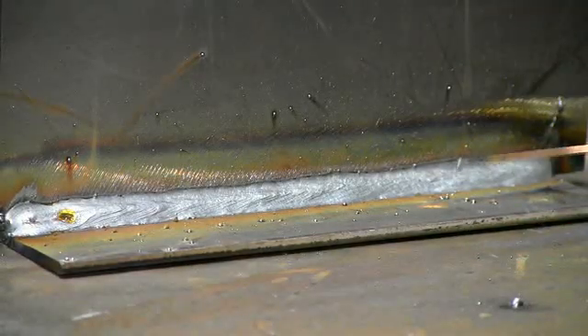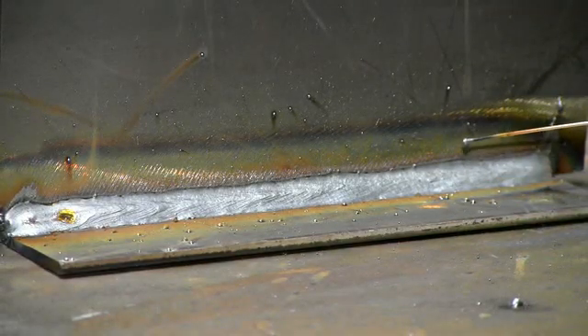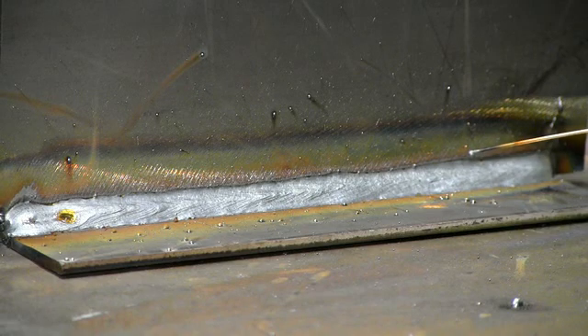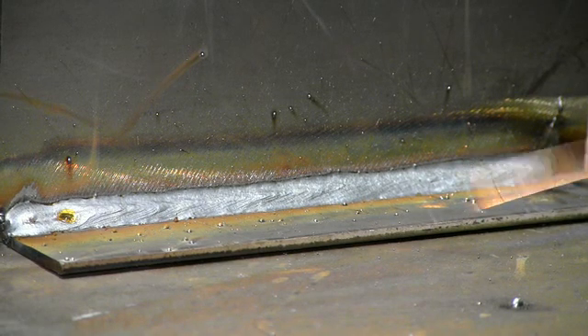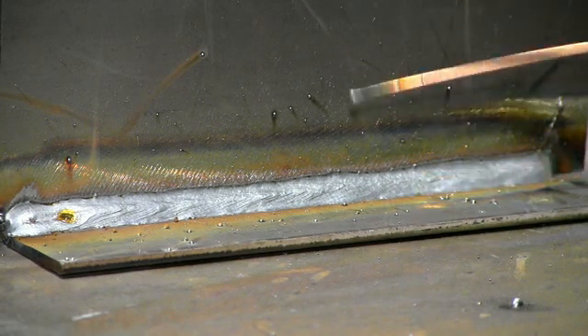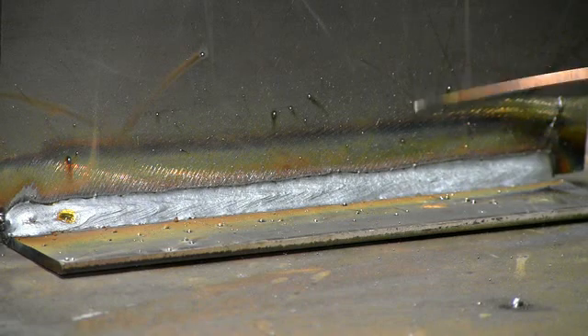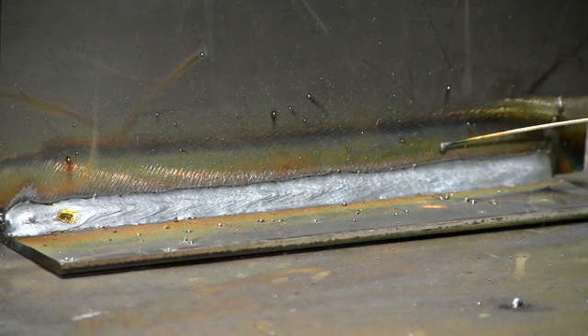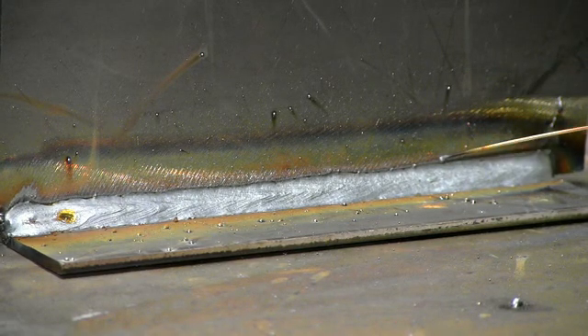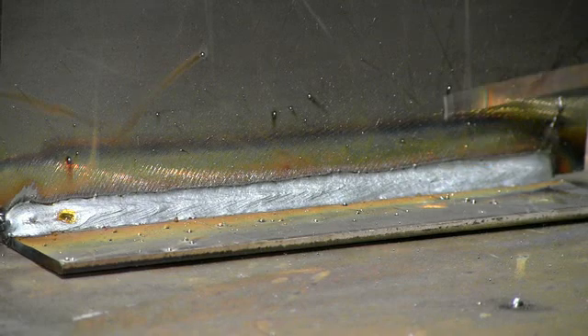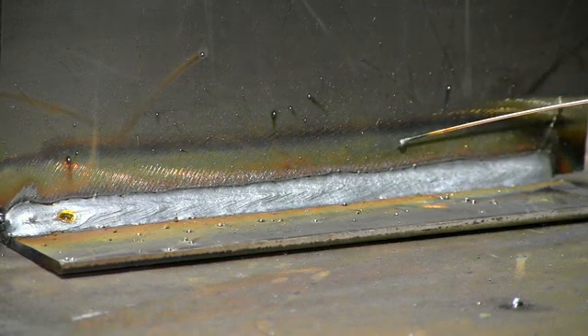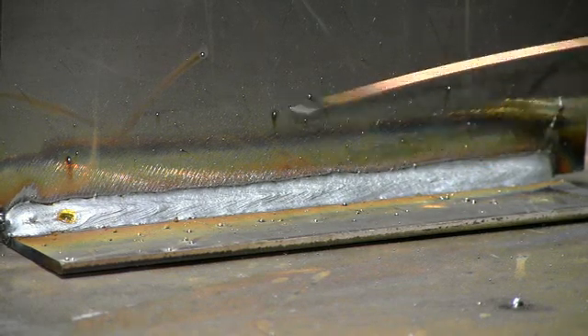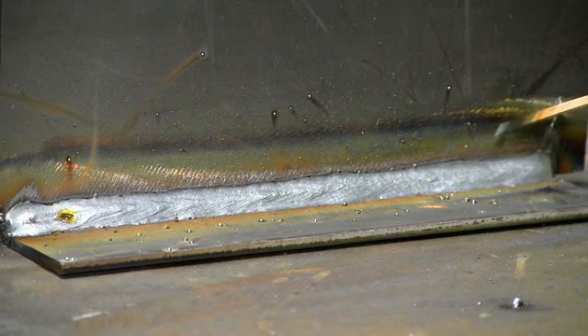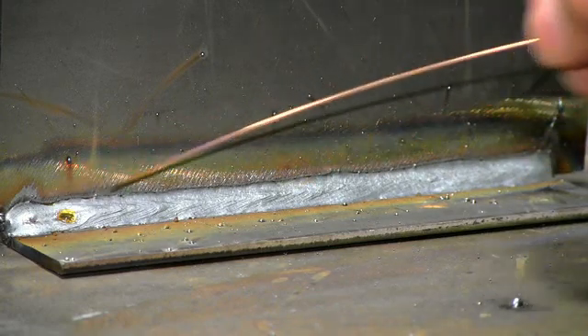So now you can see the results of welding at 700 inches per minute at 27.5 volts. Our optimum settings again were 27.5 volts and 600 inches per minute. In this test, I raised up the wire feed speed to show the impact. And so what was happening while I was welding was the electrode was kind of cramming into the puddle, and this was causing the arc to be somewhat buried in the puddle, which was causing the spatter to be generated. And you can see the evident spatter here. However, there's excellent bead shape.